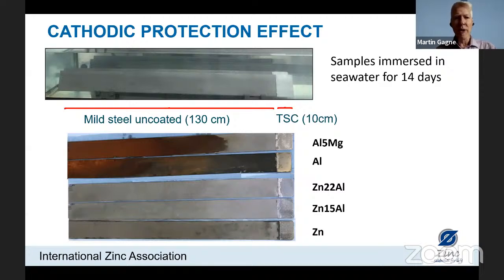In the top photo, we took some 140 centimeter long panels, and on one end, 10 centimeters, we covered with TSC, the thermal sprayed coating, a metal. We can see them below, some aluminum alloys, some zinc alloys, but we left 130 centimeters uncoated. These samples were immersed in seawater, and the seawater is the electrolyte. The thermal spray coating is the anode that's protecting the exposed steel. And we can see the results there in the bottom photos.